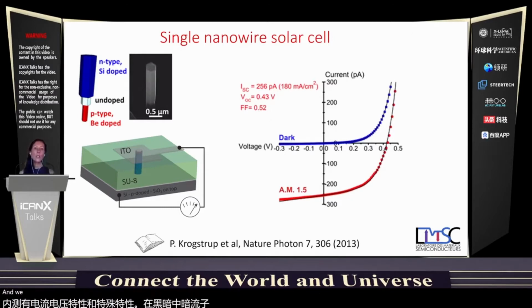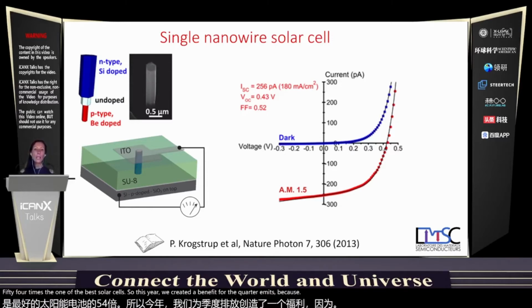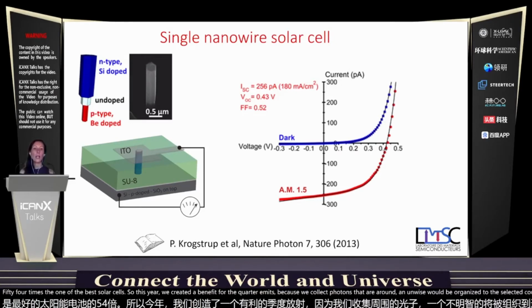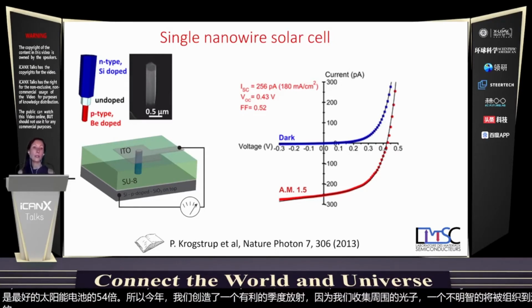And we see that we create a photocurrent that is 180 milliamps per square centimeter, which is about 54 times one of the best solar cells. So here we create a very high amount of photocurrent, and it's because we collect photons that are around the nanowires. If we normalize to the lateral size of the nanowire, this gives us a very high current density.